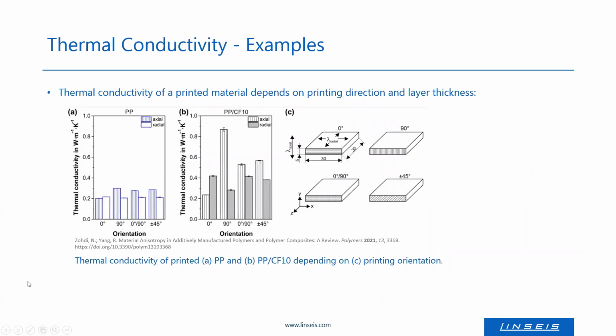But why is the thermal conductivity of interest? So thermal conductivity is more of interest for the printed material rather than the printing process, because the thermal conductivity of a printed material depends also on the printing direction and also on the layer thickness. Here you see an example of the thermal conductivity difference of printed PP and PP with CF10, and the printing was done under several orientations, which are shown here. And in this curve, you see that the thermal conductivity of the material is really influenced by the printing orientation. So by that, you can optimize your printing process in general to achieve, for example, the highest possible thermal conductivity of the material.